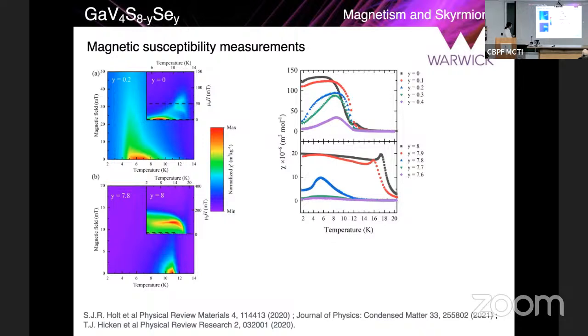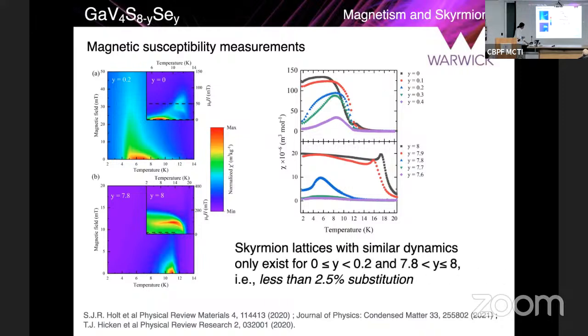And if you look at the parent compounds here for y = 0 and y = 8, you know exactly where the skyrmion pockets are. And if you look at the end materials where I said there is a possibility of observing skyrmions, and indeed we do see some evidence very similar to what you see in the end compounds, but at a very, very low scale. So you see some evidence of some change in dynamics there, which would correspond to the dynamics which are very similar to the presence of skyrmion lattices.